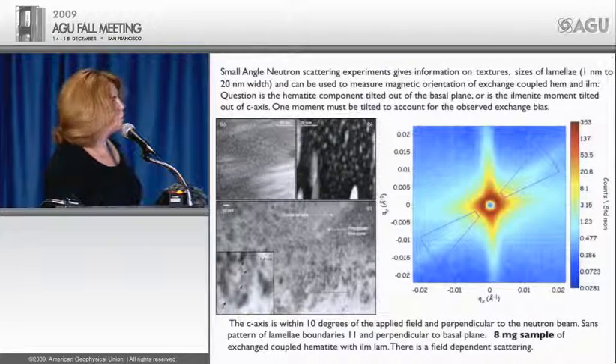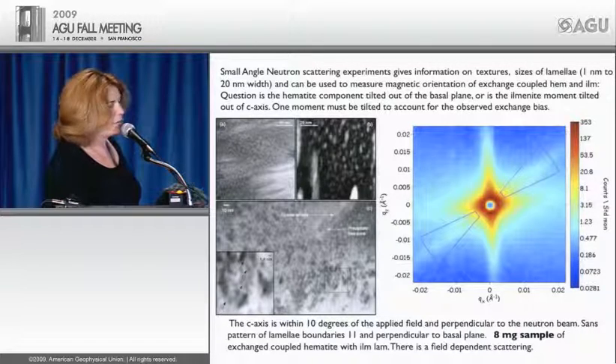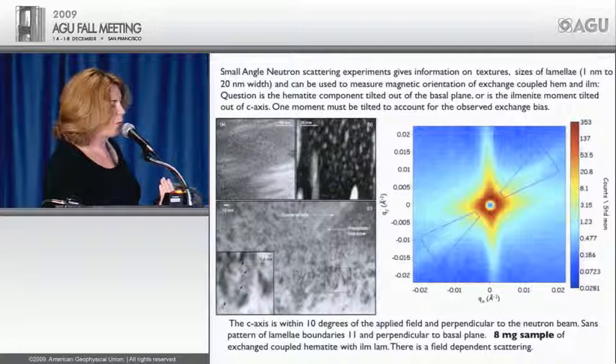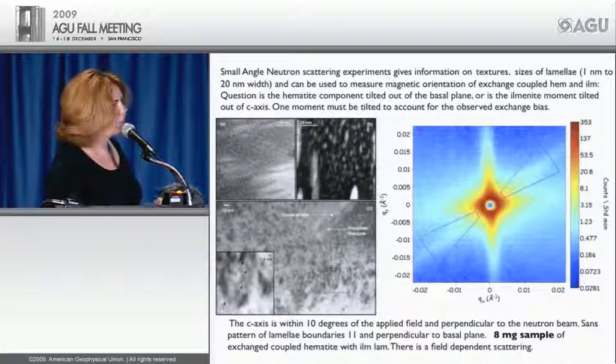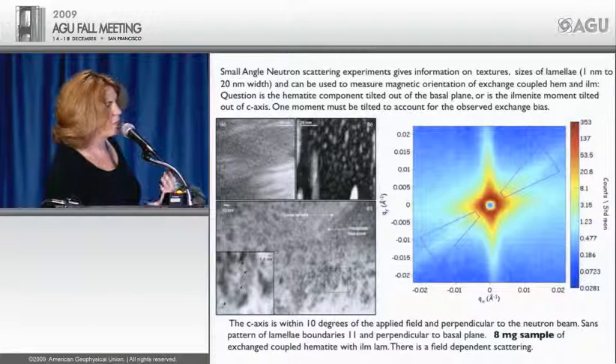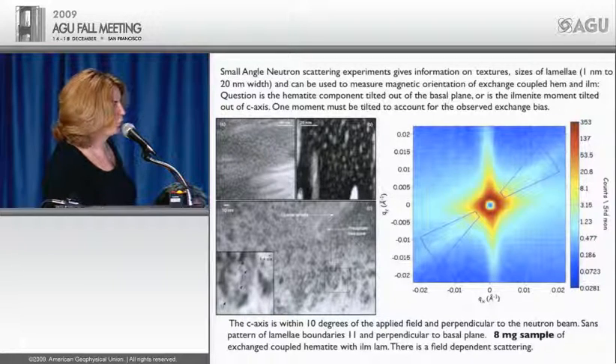So we've done quite a bit of work using small angle scattering, trying to understand the size of the lamellae, also with magnetic fields to see if we could find which way the hematite is tilted out of the basal plane, and whether the ilmenite is tilted out of the C-axis. So we could start to understand how you get these very large shifts.